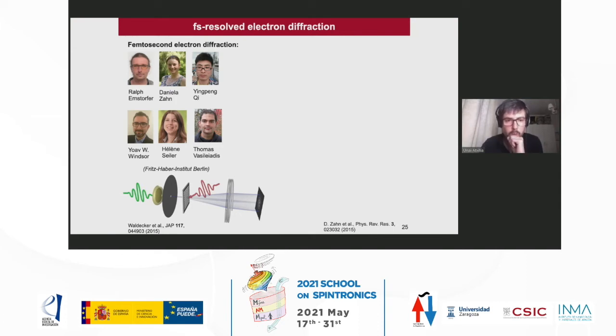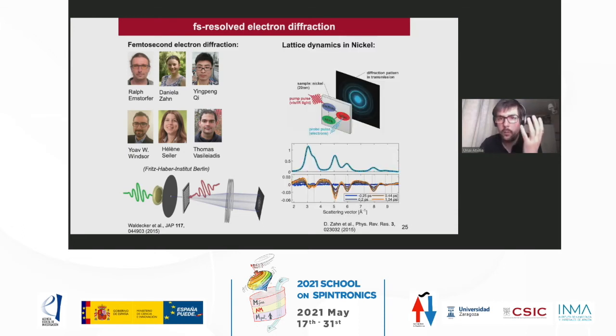They developed this technique by putting a 20 nanometer nickel sample, exciting the system with an optical pulse that goes into the electrons, hits the electrons, and then looking at the lattice by sending electrons through it. These electrons create a diffraction pattern in transmission, and by looking at the radial distribution of this pattern and how it changes over time, we can extract the lattice dynamics.